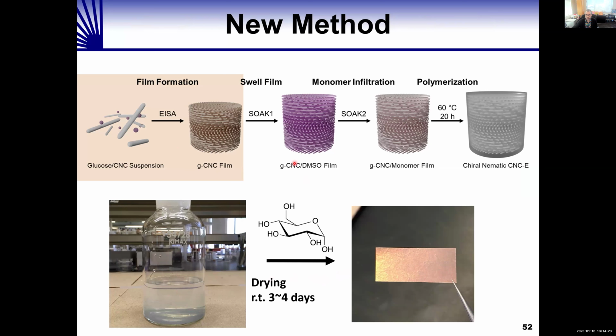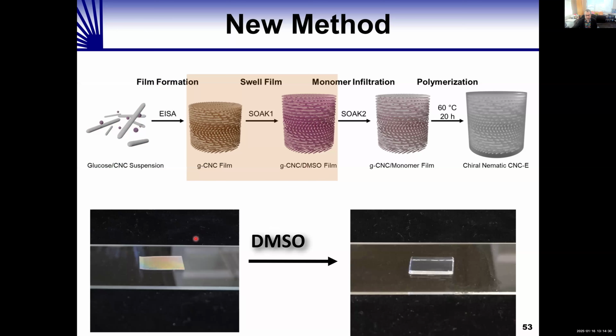The next thing that we do is we soak it in a solvent called dimethyl sulfoxide. Here's the film before soaking, and we swell it in dimethyl sulfoxide. Now it's transparent and colorless because the helical pitch is longer than the wavelength of visible light. So initially it was reflecting visible light, but when we swell it, it elongates the helical pitch so that it's now reflecting infrared light.